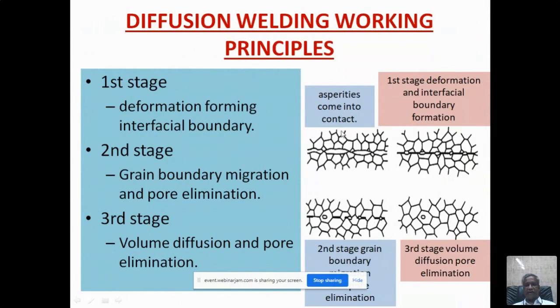Here, when you heat this material, and also apply load, because of the combination of thermal energy and mechanical energy, the contact points will get deformation. Deformation will occur at the interface, the interface between the top surface and the bottom surface. In the second stage, because it's a continuous process, it will take longer time.